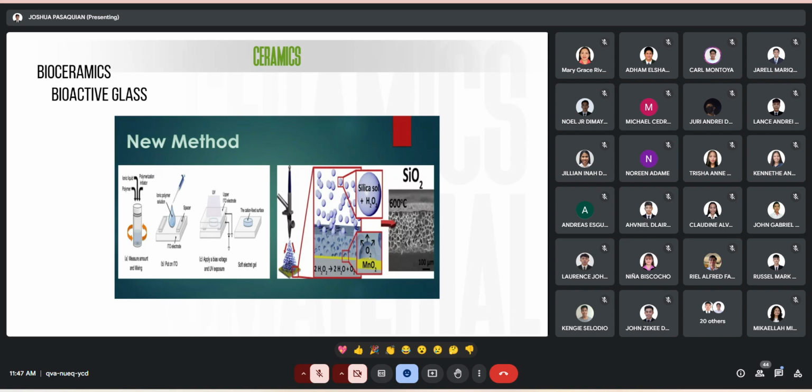for hydroxyapatite deposition. However, the interesting part about this is finding the right size for the particles, because small particles give low mechanical properties and good antimicrobial capabilities, but large particles prompt good mechanical properties but decrease the antimicrobial capabilities of the glass. Bioactive glass was first discovered or developed in 1969 by Larry L. Hench, but it's under constant evolution and development, as we will see later on. That's why I will talk about it today.